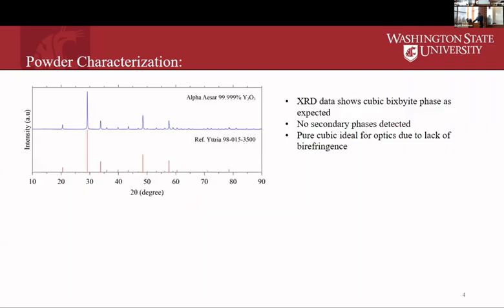So the first thing we did after looking at it with the SEM was powder characterization—we wanted to see what phase it was. Now with yttrium oxide, it's typically in the cubic Bixbyite phase, which is exactly what we want, because when you're making optics, if you have a non-cubic phase, you run into birefringence and things like that. And if your grains are not perfectly aligned, or you're not working with a single crystal, you'll get distortion of your image.